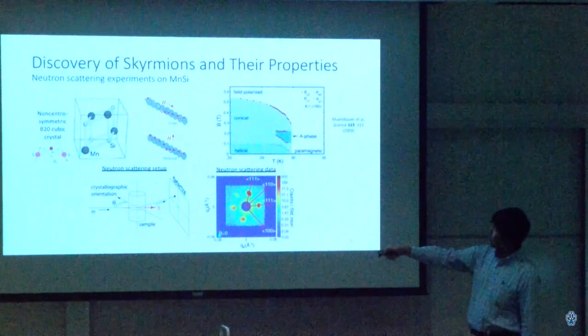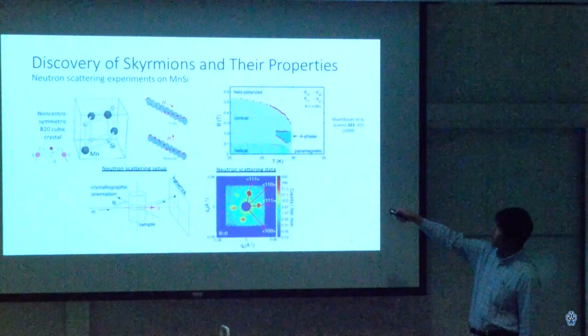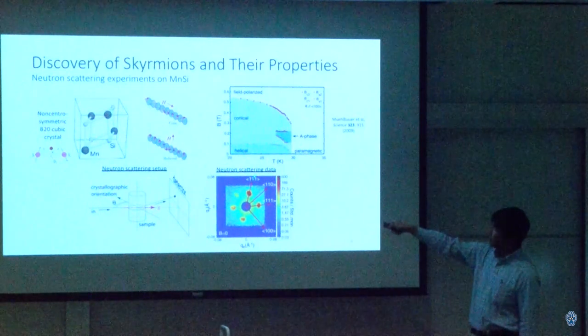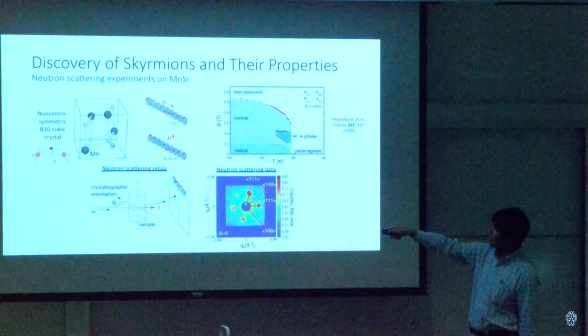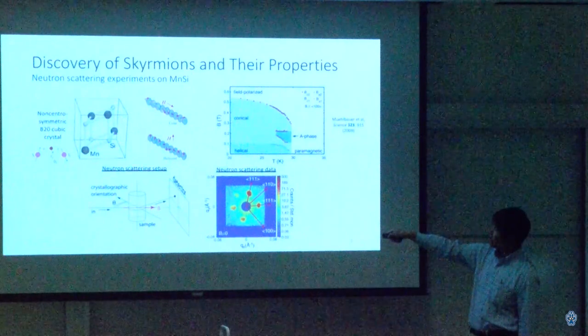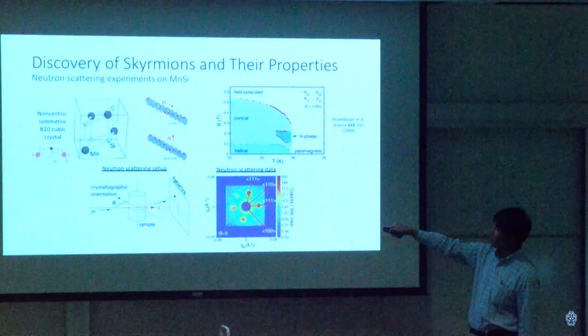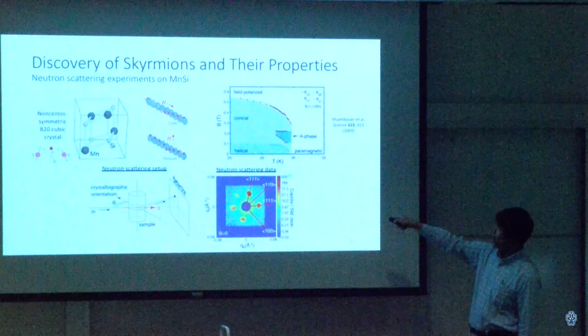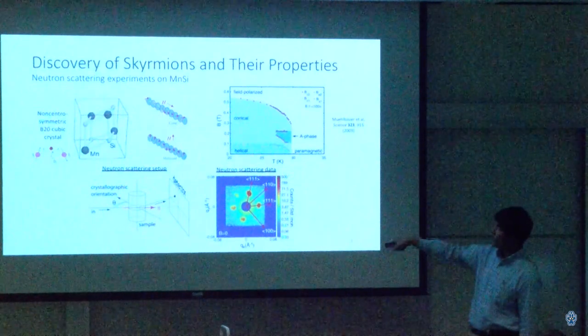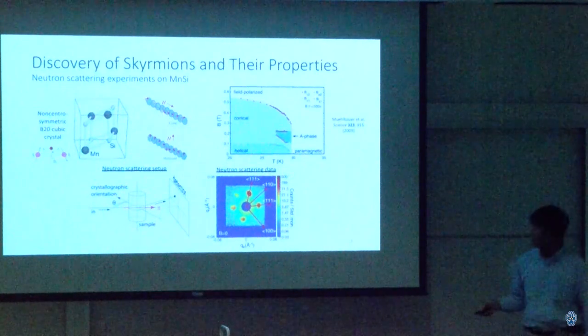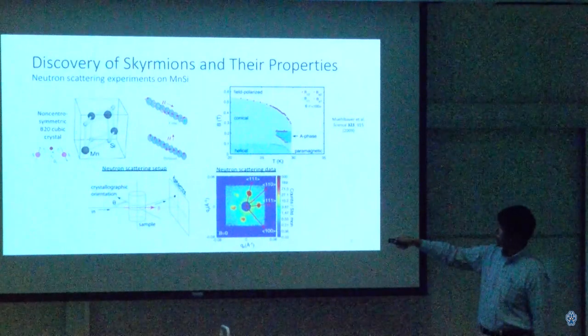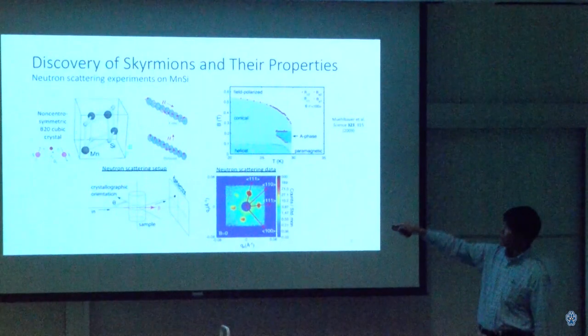This pattern is from the helicoidal state down here. And you can see that the helicoid produces diffraction spots. That's what these red spots are. Red indicates a high neutron count. Blue indicates a zero neutron count. And they tend to go along certain directions defined by the crystal structure.